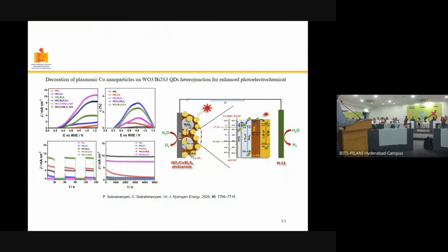But a little more sluggish part of it is the hydrogen evolution reaction. For that you need to have a P-type combination. Somehow if you scan the literature, the best catalyst comes with respect to copper. Though other combinations are well known, like Cu2O, CuO, these +1 and +2 copper based combinations are the best p-type combinations you can think of.